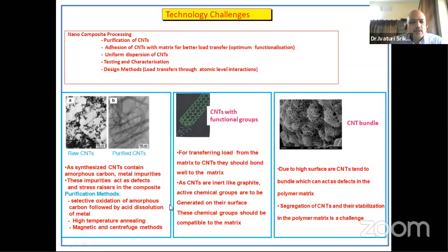To remove the impurities, what people used to do is this: amorphous carbon is unstable. It burns or oxidizes at around 300 degrees centigrade, against almost 450 to 500 degrees centigrade stability for carbon nanomaterials. So if you heat treat it in air at around 350 degrees centigrade, amorphous carbon will burn. Then to remove the metal impurities, you reflux it in some acid, nitric acid or HCl, where metals will get dissolved. So that is a typical purification method people have employed.